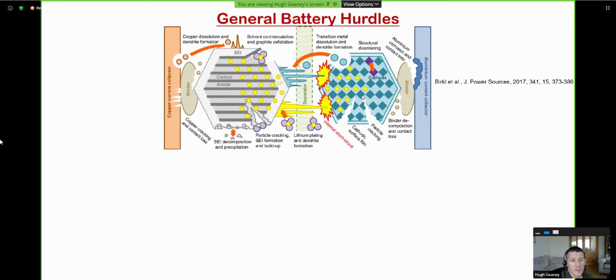On the cathode side, as we move to higher energy cathodes, they're in general more reactive. So we can have structural disordering. This is particularly true when we have high degrees of delithiation of the cathode material. We can get things like transition metal dissolution. Essentially you can leach out some of the transition metals from the cathode material that can cross over to the anode and cause all sorts of problems there. And you can have issues on the aluminium current collector as well.